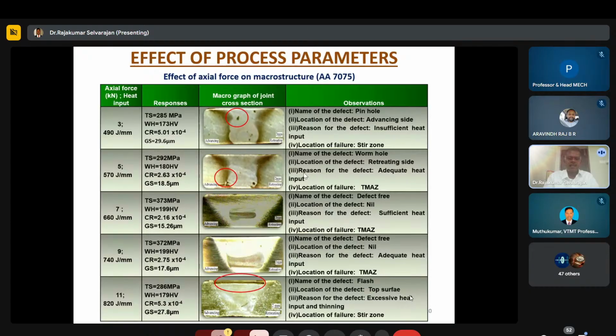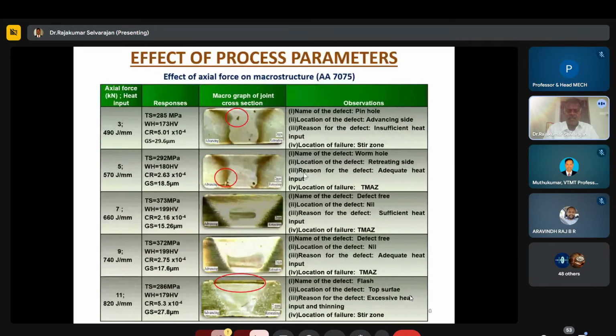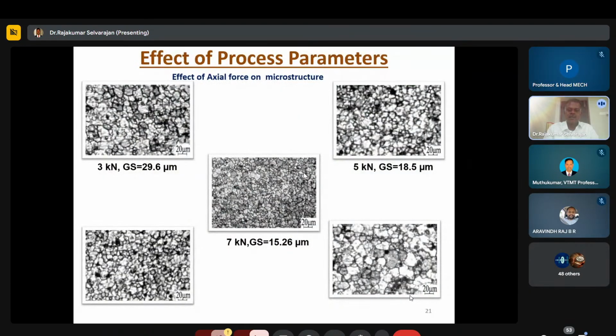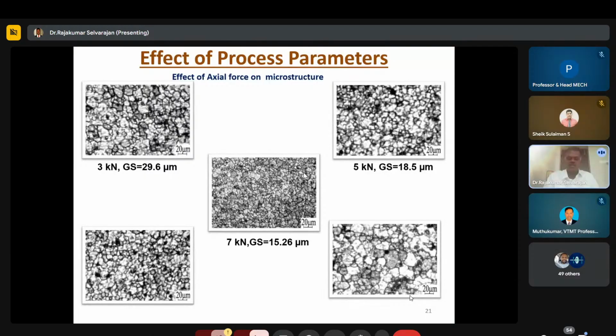Again, you can test the macrostructure. The 3 kilonewtons gives a pinhole defect in the advancing side, and the 5 kilonewtons gives wormhole defects in the retreating side. And you can see defect-free joints at 7 kilonewtons, which also gives better mechanical properties when compared to the other axial forces. Then you can go for the optical microscope, and you can see that 7 kilonewtons gives a grain size of 15.26 micrometers, while the others are larger. So 7 kilonewtons gives good mechanical properties.